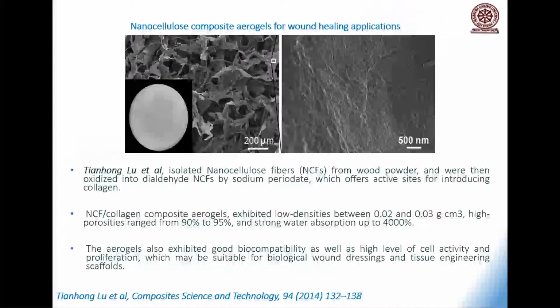My Chinese colleague, Professor Lu, and co-workers, you know what they did? They made a hybrid configuration of nanocellulose and collagen. They combined nanocellulose and collagen. And Professor Lu has made a beautiful aerogel. And you can see the porosity of the aerogel, 95% porosity. And the water holding capacity, look at the water holding capacity. The water holding capacity of this aerogel is something like 4,000%. You know, Professor Lu started a company in China. And he projected it as a wound dressing material for patients, because it can absorb all the pus and water from the wound. And he said this is a good platform for introducing antibiotic.